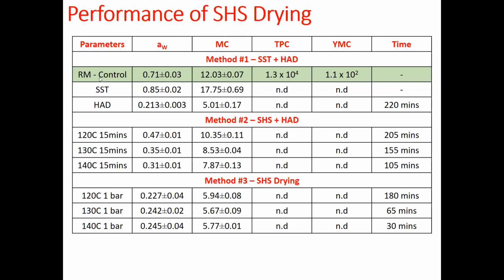If you look closely, when you expose your raw material to the saturated steam treatment, the water activity is about 0.85. The moisture content has also increased. When you have an increment of this, you get a very high drying load, meaning it would take a longer period of time to dry your product to the moisture content that you would like. But in terms of the total plate count, it's not detectable, and this is also not detectable. For the hot air drying, it managed to lower the water activity to 0.2, and the moisture content is about 5. But the processing time it takes to get this value is about 220 minutes.